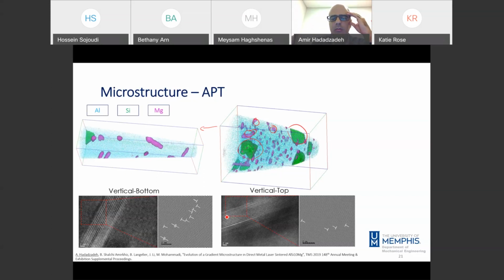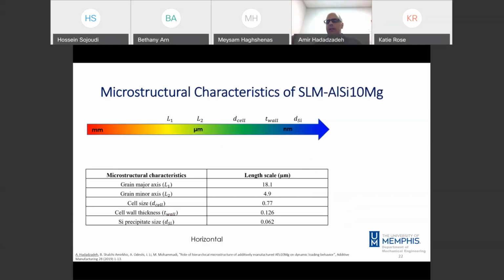So here on the top, we have a fully coherent precipitate with the matrix. Over the interface, we have probably a couple of dislocations because of the mismatch between the precipitate and the matrix. But at the bottom, as you see here, more dislocations evolve in the structure because of the mismatch.